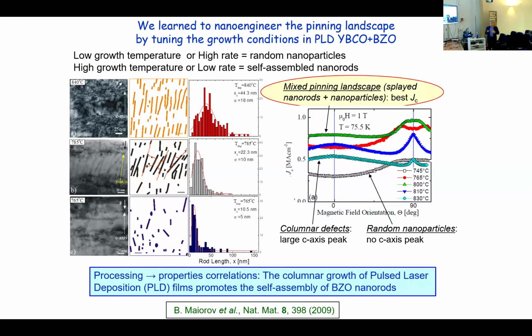Okay, so this is an example of processing-properties correlation. The columnar growth of the PLD, these are PLD coated conductors. The columnar growth of pulsed laser deposition promotes the formation of the self-assembled nanorods.